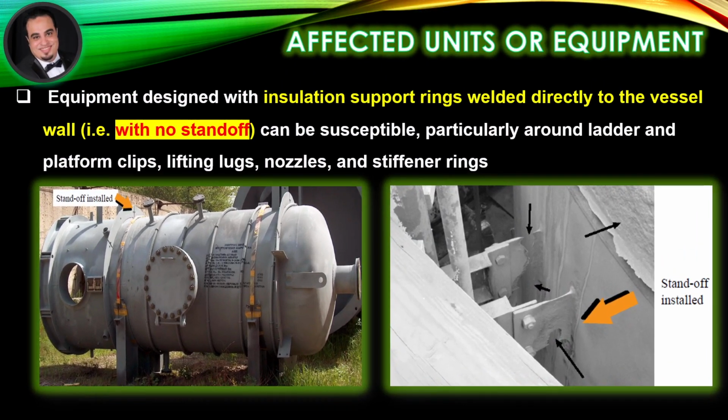Equipment designed with insulation support rings welded directly to the vessel wall, for example with no standoff, can be susceptible, particularly around ladder and platform clips, lifting lugs, nozzles, and stiffener rings, as illustrated in figures.